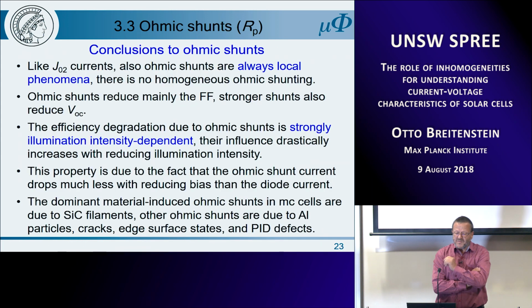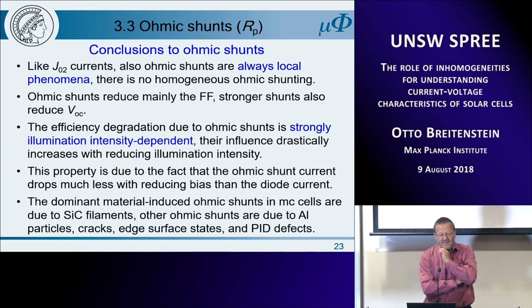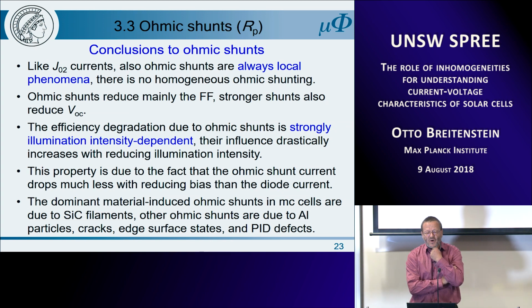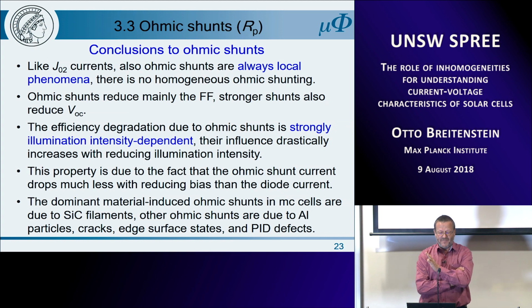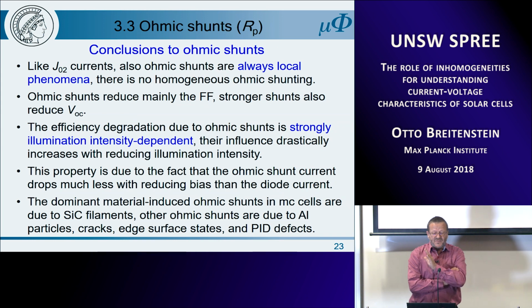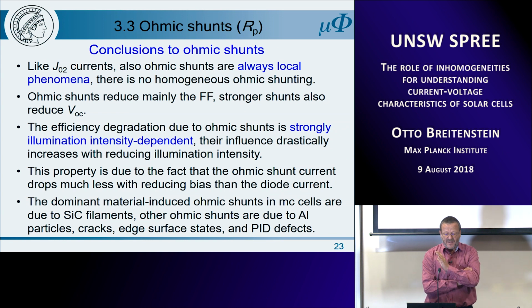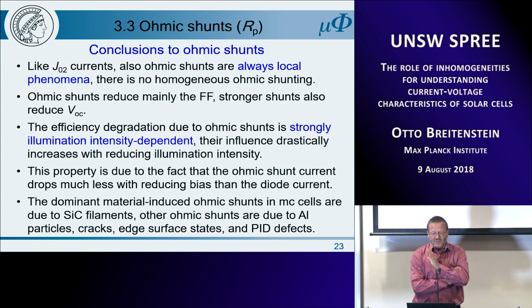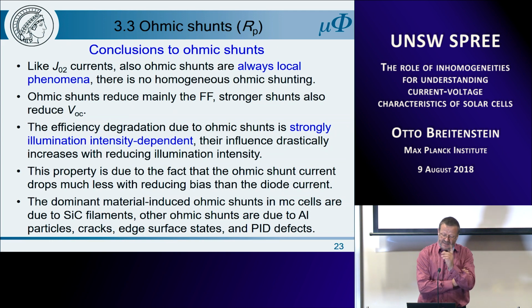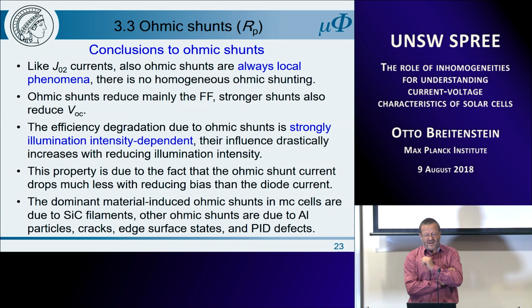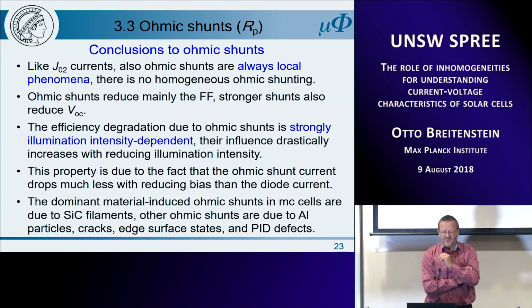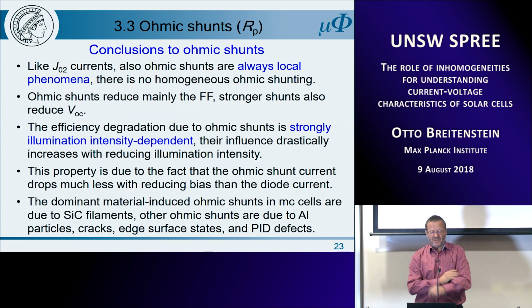So this brings me to the conclusion on ohmic shunts. Like the J02 currents, ohmic shunts are always local phenomena. There is no homogeneous ohmic shunting. Ohmic shunts reduce mainly the fill factor. Stronger shunts also reduce VOC. So the efficiency degradation due to ohmic shunts is strongly illumination intensity dependent, as I've shown at the beginning. Their influence drastically increases with reducing illumination intensity.